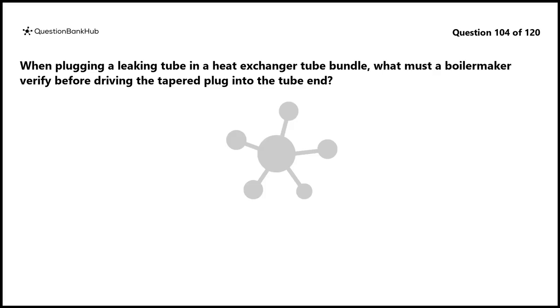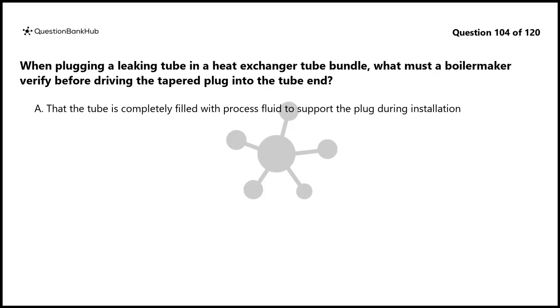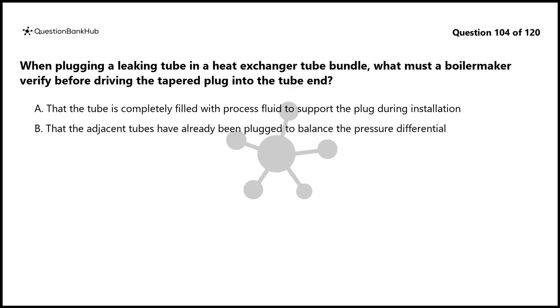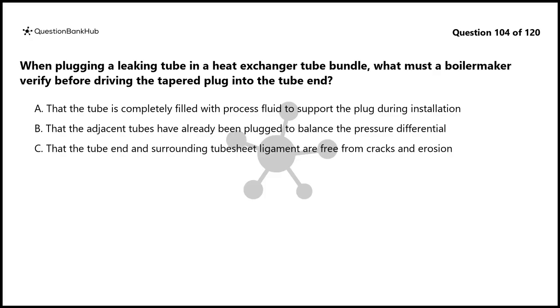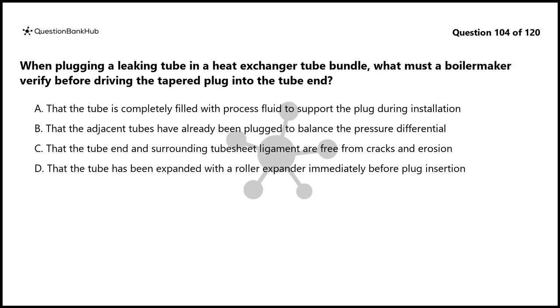Question 104. When plugging a leaking tube in a heat exchanger tube bundle, what must a Boilermaker verify before driving the tapered plug into the tube end? A. That the tube is completely filled with process fluid to support the plug during installation. B. That the adjacent tubes have already been plugged to balance the pressure differential. C. That the tube end and surrounding tube sheet ligament are free from cracks and erosion. D. That the tube has been expanded with a roller expander immediately before plug insertion.